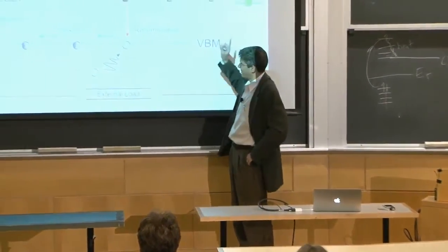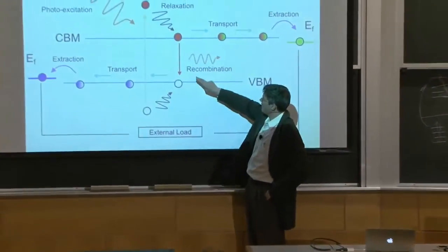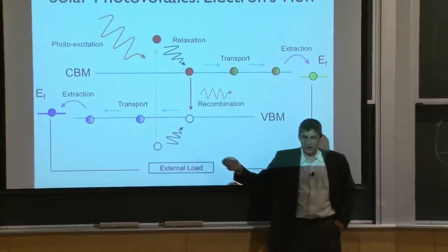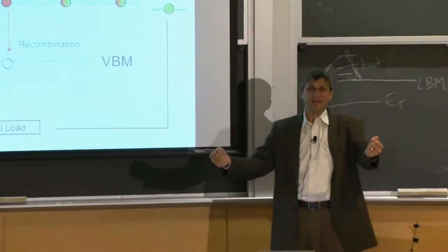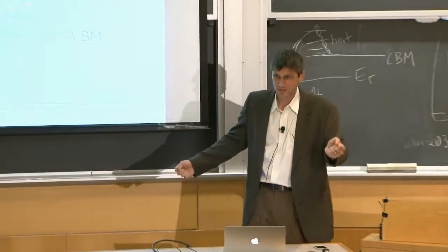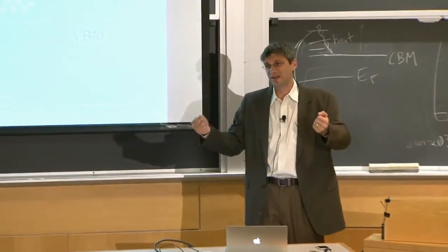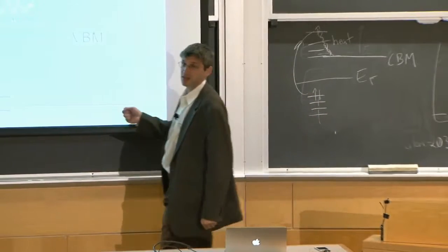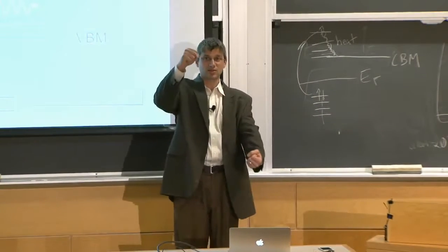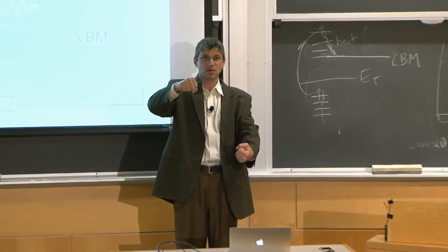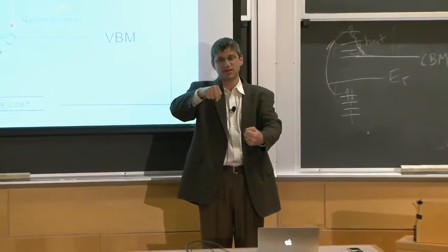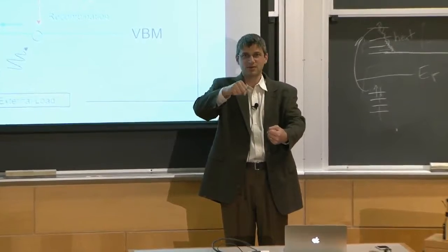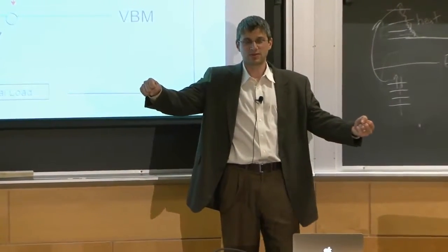So, fact of the matter is, where was I? Anyway, they don't like each other much. They like each other a little bit, like a milli-electron volt or two of binding between that electron and the hole in silicon. So basically, as soon as that electron and hole form, and one is in the conduction band and the other is in the valence band, they just wander off, okay?